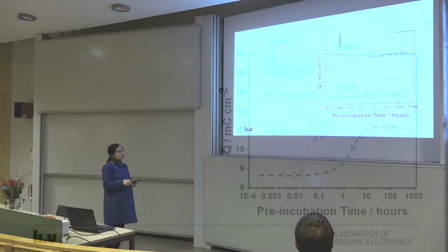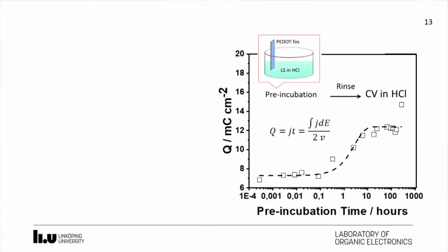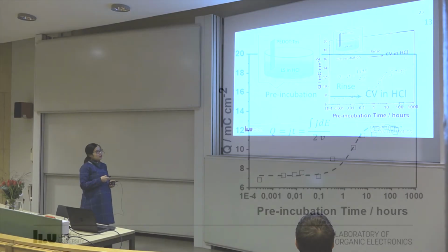Besides that, we also studied the effect of pre-incubation time on the adsorption. As shown by the integrated charge, we found that the lignin sulfonate adsorption increased with longer incubation time, and after 5 or 6 hours, it starts to get saturated. So this can be a guideline for lab treatment. It's just interesting for us.